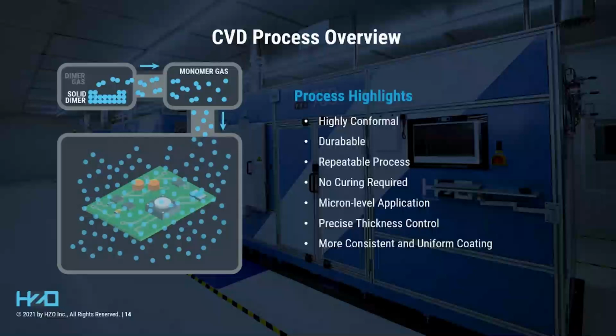It starts with a solid dimer precursor, which is illustrated on the upper left, which is sublimated at around 150 degrees C, passes through a pyrolyzer, on the upper right of the diagram, which is around 600 degrees C, and it cracks the dimer into two reactive monomers, which are then pulled into the vacuum chamber by the pump with the product inside, at which point those monomers are polymerized in situ, creating a coating on the product.